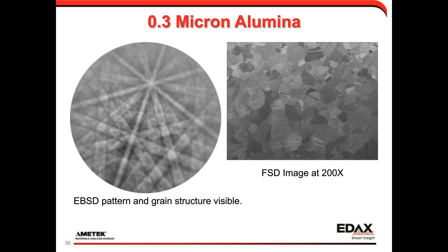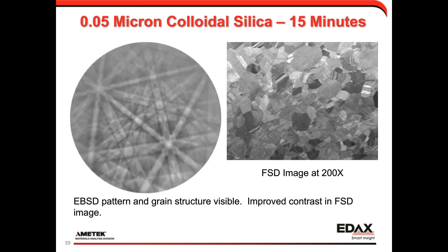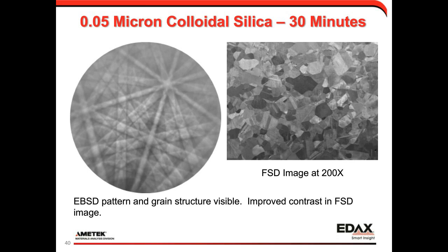Here with 0.3 micron alumina for 10 minutes, the pattern again is visible, a little bit better grain structure, but now the concept of comparing patterns by eye, which one's better, becomes a little bit trickier, and so we'll step through these. This one's now using the 0.05 micron colloidal silica, 15 minutes, really improved contrast in the FSD image. This is now 30 minutes with colloidal silica. I've still put improved contrast, but it's a little difficult to really see visually.